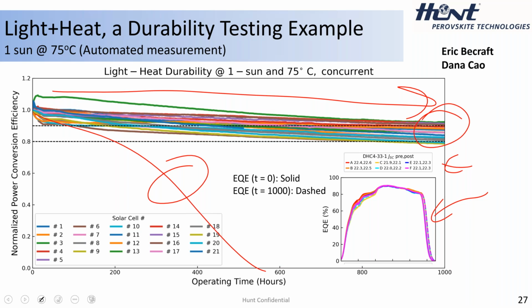If you had decomposition, typically what we see is it's elsewhere in the device, usually at an interface or an electrode surface, something of that nature. So it's the device itself that tends to fail under these stress tests, not the material. That's something I wanted to highlight. And we believe this is, again, in large part because of our chemistry approach. We are making the material itself as fundamentally robust as possible and then designing a strong architecture around it.